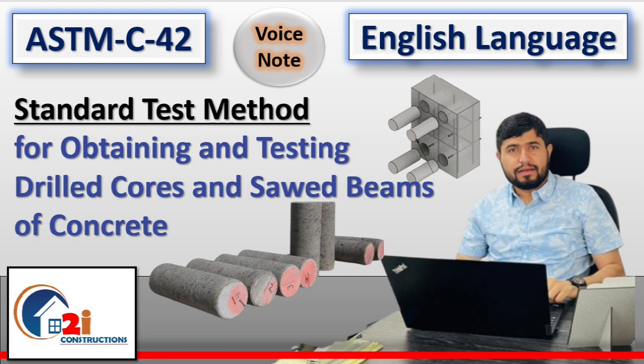If any of the cores, for example, we have 2 at 95%, but one is 74%, the whole test is rejected. This sample is rejected, it failed. And also, for example, if we have 90 and 2 at 76 or 75, but the average comes to 83 or 84, again it's failed. It's not acceptable. So the average of 3 should be 85 or greater, and none of the cores shall have a compressive strength less than 75% of the design compressive strength of that member or structure. Thank you.